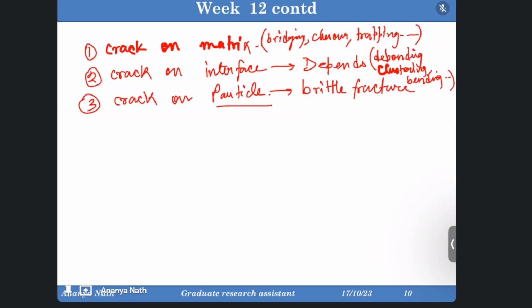So if there are some sharp corners present over the particles which are embedded in the matrix, then they can act as the crack initiation point. Near that region of the sharp corner, the stress intensity can be more, and due to which, if there is a stress field generated over there, there will be a pile of stress, and that stress field or the stress intensity will lead to some crack initiation.